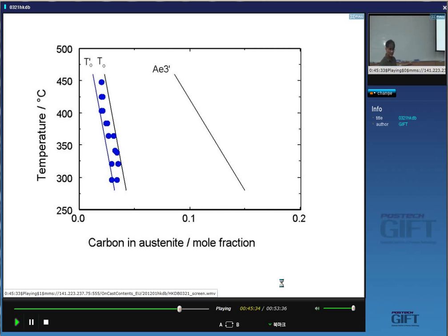So this proves that when bainite forms, it forms exactly like martensite, but then the carbon escapes from the plate. So the growth of bainite is diffusionless, but the carbon then escapes because we are operating at a high temperature. And these days, you are trying to do that with martensite in designing the quench and partitioning steels. So that's quite an important result. And from this result, we make many predictions, which we then have to verify experimentally.